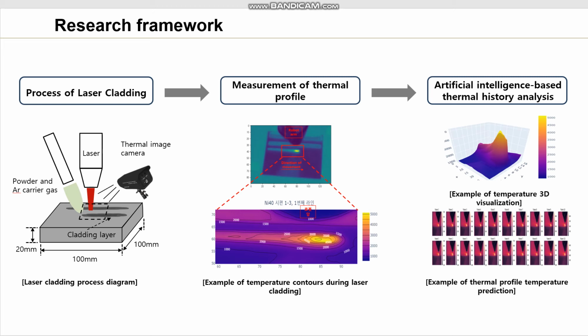In addition, the thermal profile of the heat effective zone varies depending on the chemical components of the substrate and powder and process conditions. So, in this study, we first quantified the temperature distribution around the laser beam and the behavior of the heat effective zone over time during laser cladding using a thermal imaging camera. And then, deep learning was used to predict thermal profile images of a laser cladding process under different operating conditions.